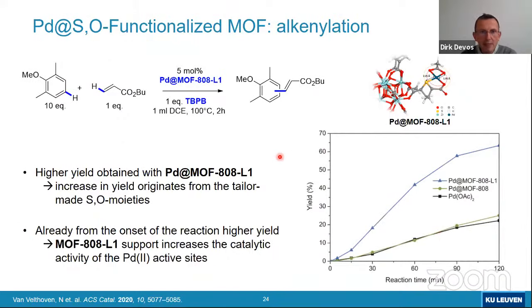And then to the catalysis. Actually in this case, we decided not to use oxygen, and I will detail the reasons immediately. And we wanted to use now this material for doing alkenylations. And the model reaction that we selected was this arene, and we wanted to alkenylate that with butyl acrylate, and then you would of course make this cinnamate type of molecule.